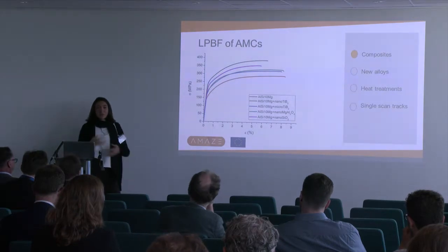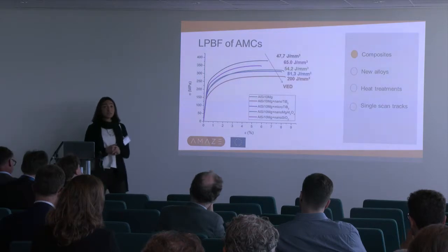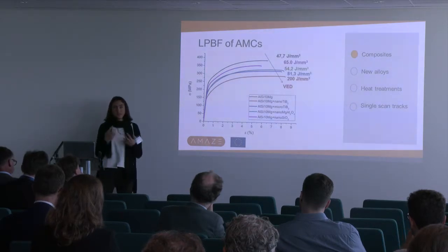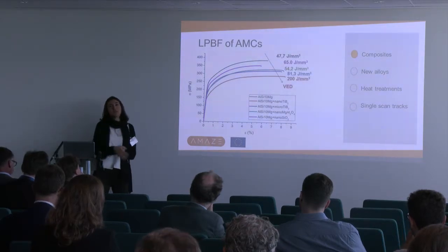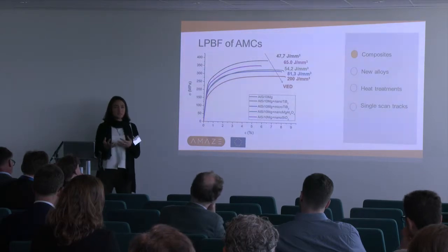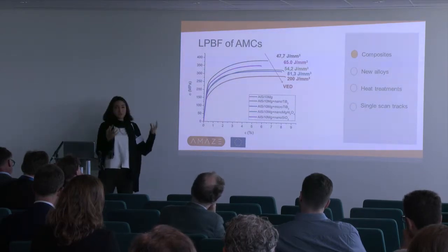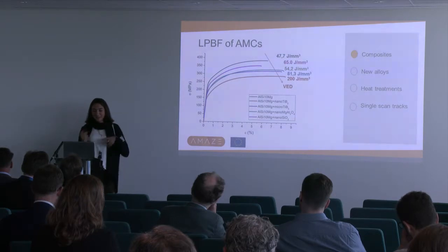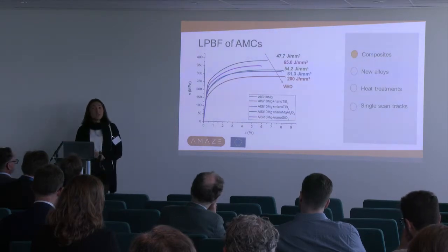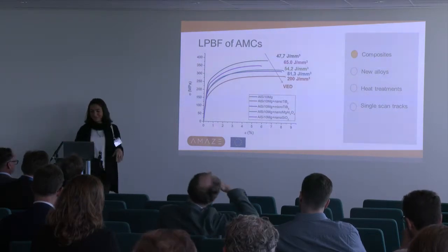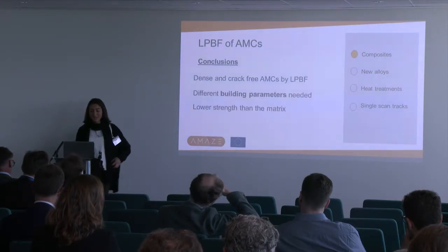So we were wondering what was going on, and what we observed is that there was a correlation with the energy density, so with the parameter we were using to produce dense composite, and so it was not possible to produce dense composite with high mechanical strength. So we had to change way to increase higher mechanical properties.